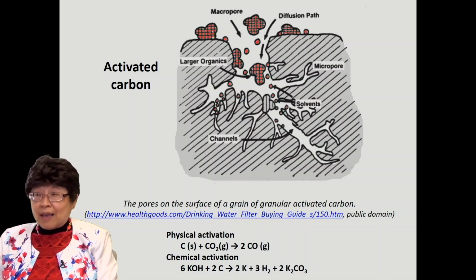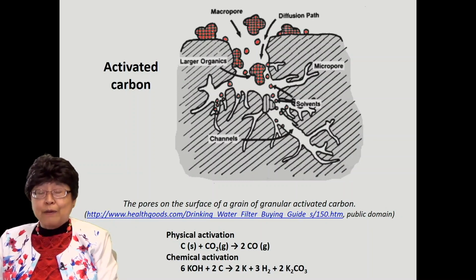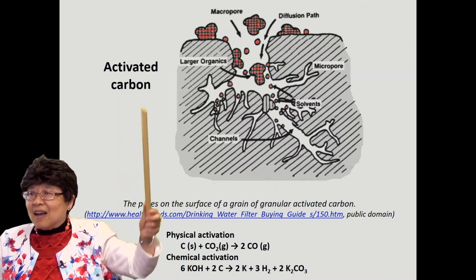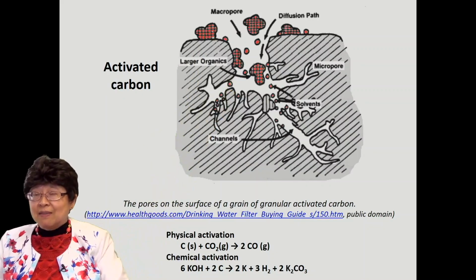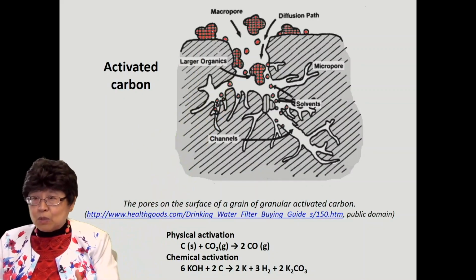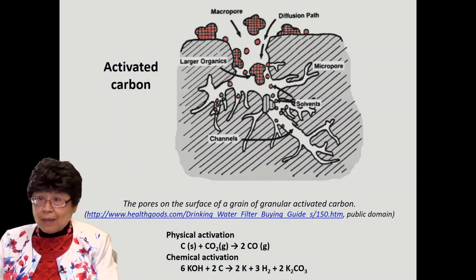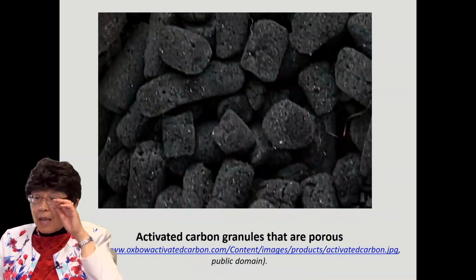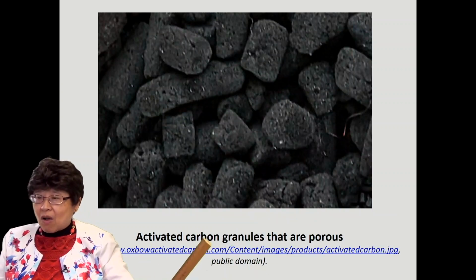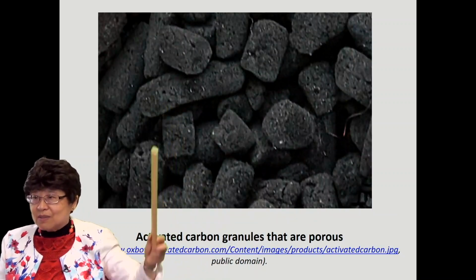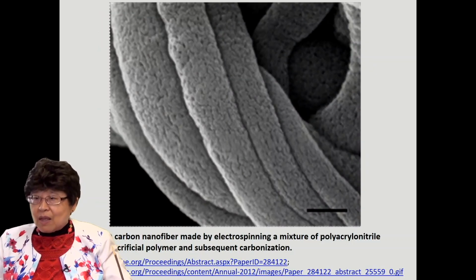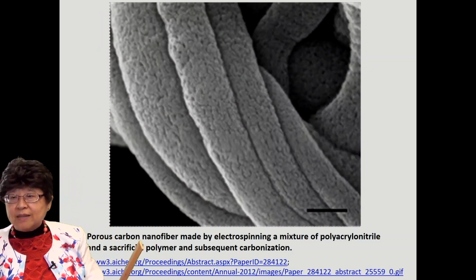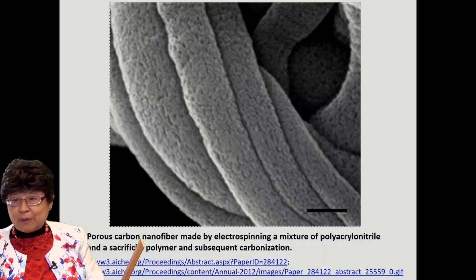So as a result, you get a lot of surface area per unit volume in activated carbon, and the junk can lodge into the pores, and thus the activated carbon is able to purify gas or liquid. And this is the most common activated carbon in the form of granules, porous granules. And this is a more exotic form, which is carbon nanofiber that's been activated.